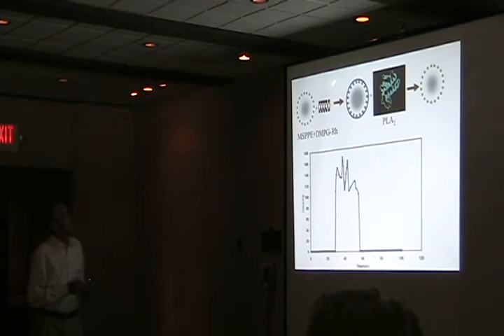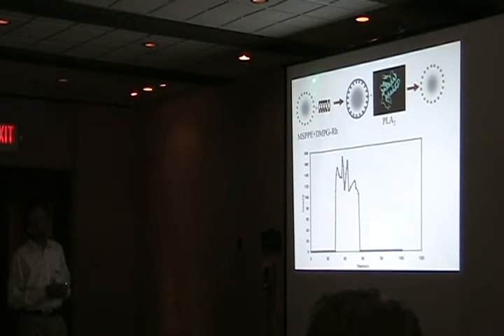What we've been doing recently is a similar experiment, where we coat the polymer-coated microspheres with a bilayer. This time, we use a small amount of the bilayer with the rhodamine fluorophore in there. And what we find is, when we do that, the polymer fluorescence is almost completely quenched. And then, of course, as we add phospholipase and we remove the bilayer, we can see the polymer fluorescence come up. We're just doing these experiments right now. This just shows that when you add Triton in the presence of the rhodamine and remove the bilayer, then the fluorescence goes down.